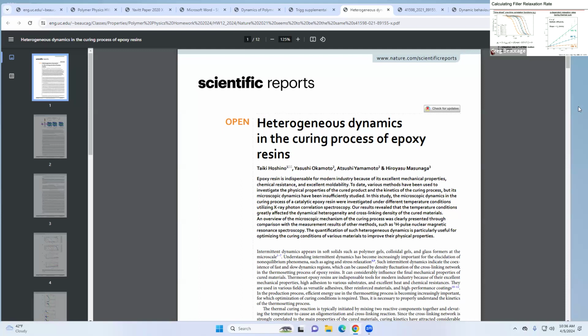But what you can see is that at 85 degrees in that pre-cure state, we've got a certain slope here. At 111, it increases, right? So if my slope is increasing, what's happening to my dynamics? It's getting faster. It's getting faster when I'm heating it up. I thought it was curing. What's going on here?